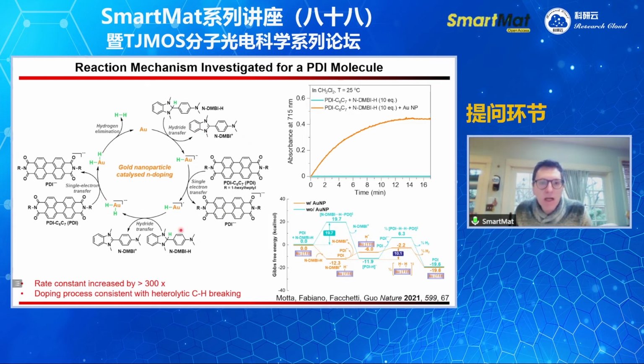If you look at the catalytic cycle, there is no species which we can stop or quench the reaction at to understand exactly what's going on, right? Because you only start from this molecule and form the radical cation, and you start from the perylene molecule and form the radical anion. So it is extremely difficult to quench the reaction, or what is called trapping intermediates, to understand exactly what the route is, and whether there are very different routes. So it's going to be extremely challenging to trap actual species. I think this is a very reasonable mechanism, at least for this small molecule.